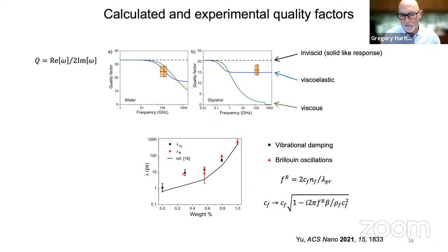These black dots are the relaxation times from the experiments of the nanoplate vibrations in different liquids. These are all water glycerol mixtures with different weight percents of glycerol. And so we measure relaxation times going from hundreds of picoseconds down to about a picosecond for just pure water. The solid line here is the literature values for the relaxation time. And then the red line, or the red experiments, is from the Brillouin oscillations.